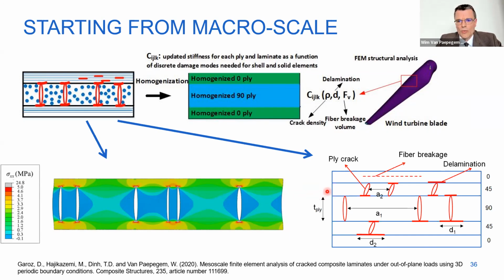On the other hand, we went in the direction of more analytical models with the variational approach, where you try to solve the system where you do have ply cracks, you do have delaminations at the ply crack tips, and you might have fiber breakage for a certain layout, and you try to solve this system without finite elements. I will show you in the next slide how we do this, but if you can do that, then you could say I homogenize these plies with their damages inside, and the stiffness tensor becomes a function of crack density, delamination lengths, and fiber breakage volume. This is, of course, under the assumption that you stay with physics-based damage models and that you try to keep a link with physical representations of damage.